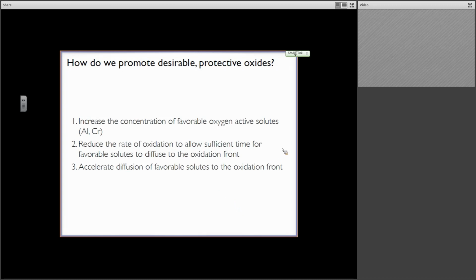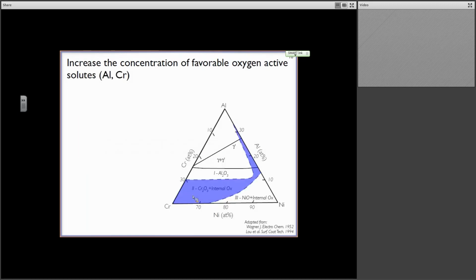Another strategy that we see in some niche applications is we just slow down the rate of oxidation. So we might have a low alloy, meaning we don't have a lot of these solutes, but if we slow the process down, we can allow sufficient time for these favorable solutes to actually get to the oxidation front and form the oxide that we want. And then the third is a little bit less common, but we can also take an alloy that has a low concentration of these oxidizing solutes and accelerate the diffusion of those solutes to the surface. Okay, so these are the three strategies that we have at our disposal, and we want to do this without